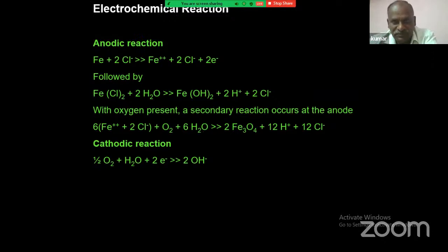When chloride is coming, that is a much faster way of corrosion process. If the chloride is not there, the initiation process is very, very long. In our model, the initiation of corrosion will be very long. When the chloride penetrates inside, the initiation period is very short. So we have to avoid the chloride penetrating inside the concrete. So that is the condition.